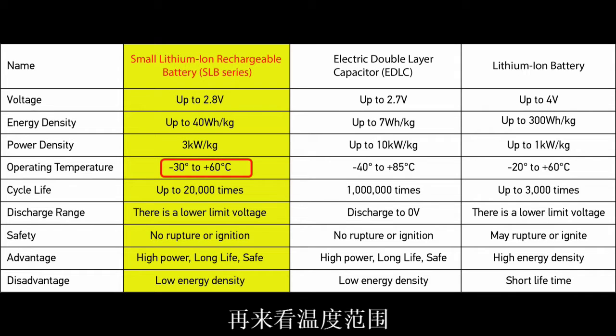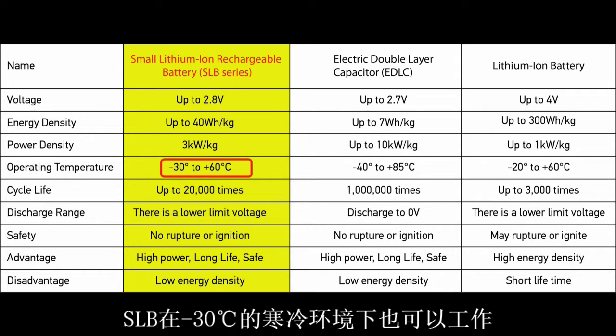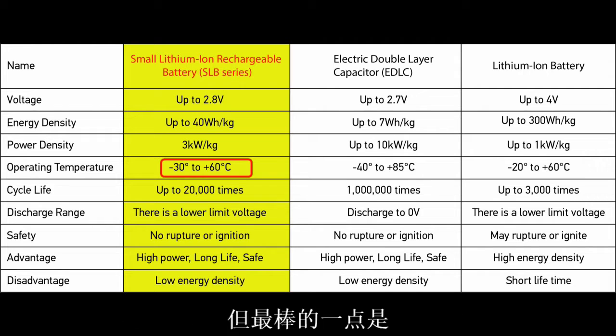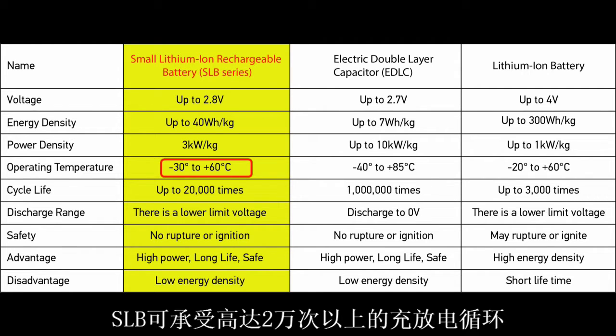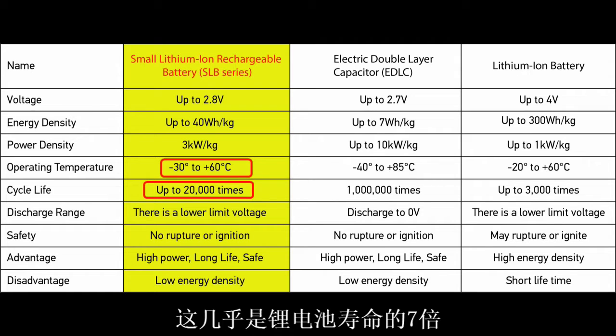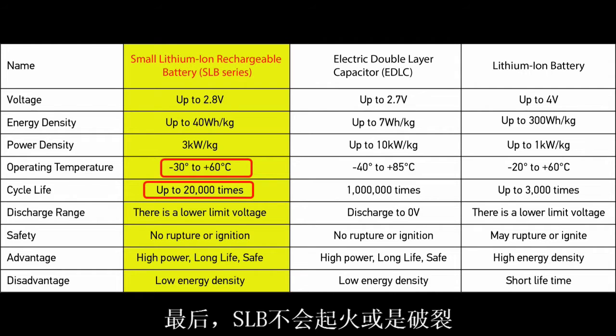And if you look at the temperature range, you will see that it has a lower operating temperature at minus 30 degrees Celsius. But the really great thing is that it can withstand 20,000 charge or discharge cycles. That's almost 7 times more than a lithium ion battery. And finally, the SLB will not burn or rupture.